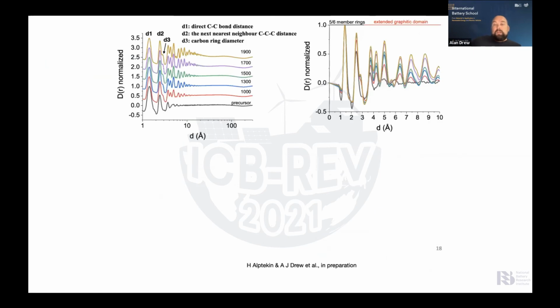Okay, so here are some results. Let's start by looking here. We normalize to the first peak. Okay, and then you can immediately see, as you increase the temperature from the precursor through to 1900 degrees C, that the peaks sharpen. This is normalized here, so this is a real amplitude change. The peaks sharpen. That means we get more ordered.